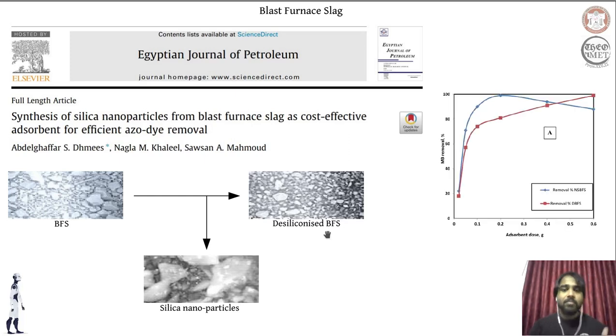Now we are using both the components that get synthesized from the blast furnace slag. One is the silica-rich gel, which is transformed to silica nanoparticles, and the remnant of the silica-rich gel. Both are being used to manage or trap this dye, and as you can see, both of these do an appreciable job in trapping these and decontaminating the water from the dye.